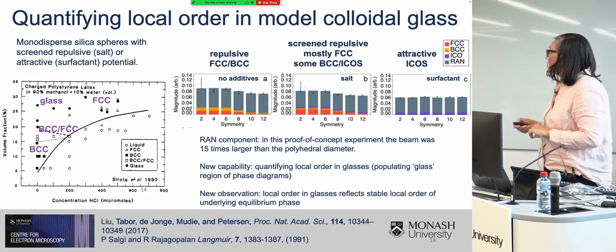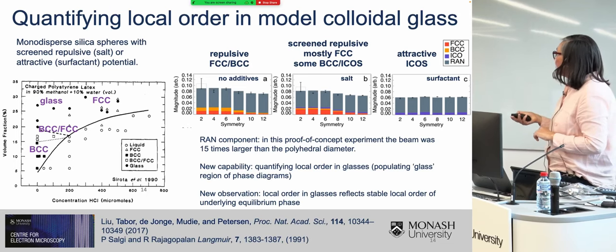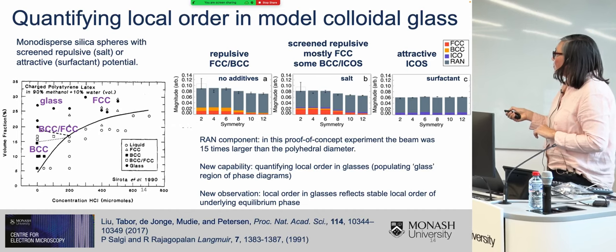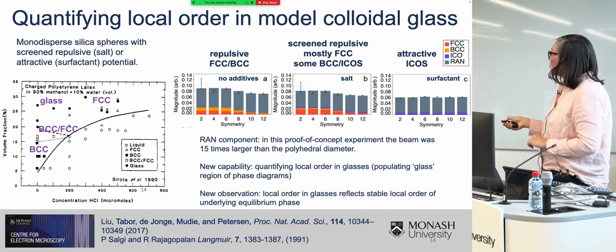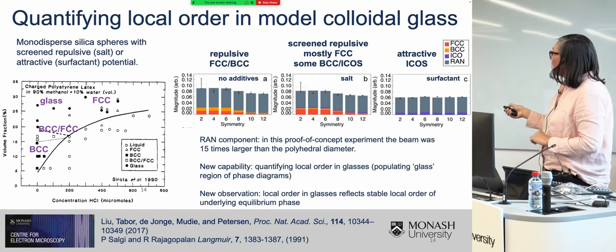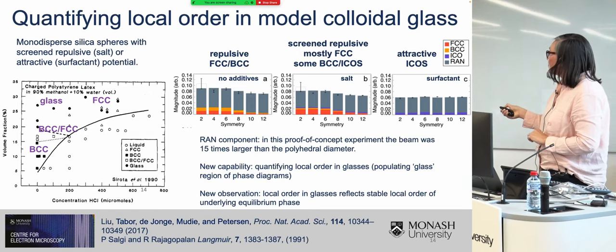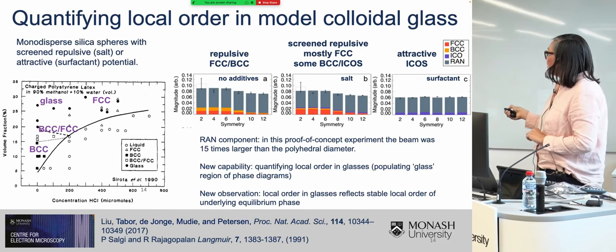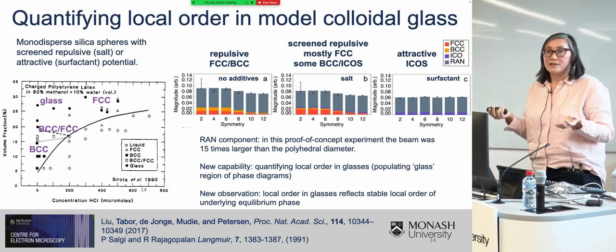So I made several different colloidal glasses with different kinds of additives, and you can see that the results are quite interesting. So here, when the interaction is repulsive, when I fit the average Fourier coefficients from my glass, I get a large proportion of BCC and FCC clusters contributing. When I screen the interaction by adding some salt, then I get more FCC clusters and a small amount of BCC and icosahedral clusters. And then when I make the interaction attractive by using a surfactant, the only measurable signal I get is from icosahedral clusters.